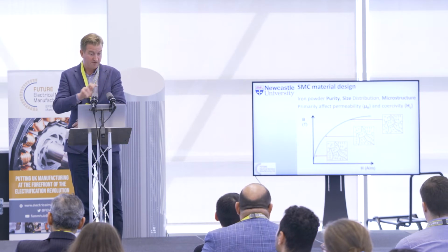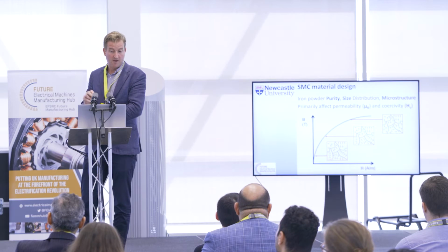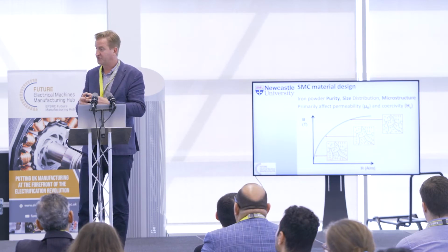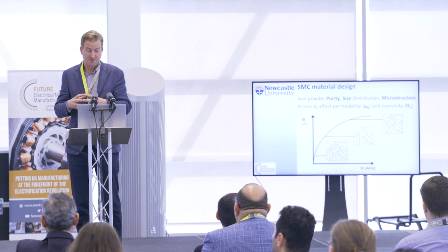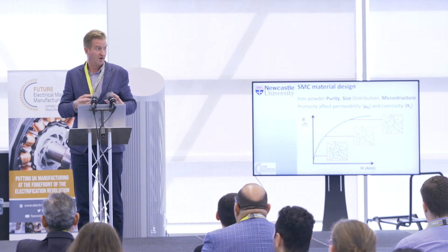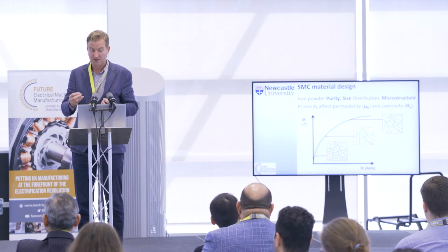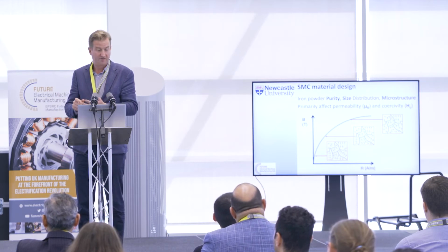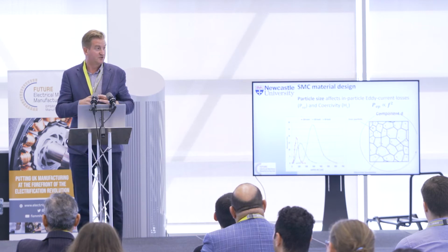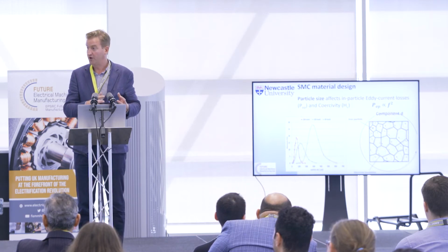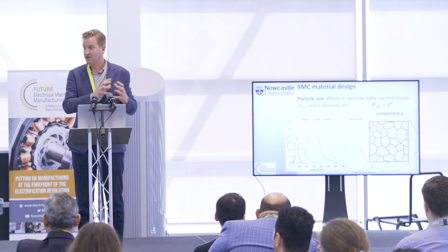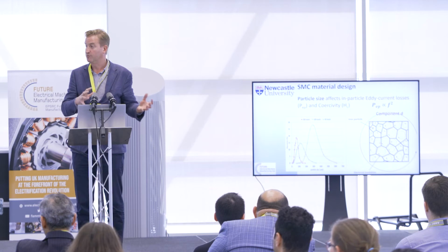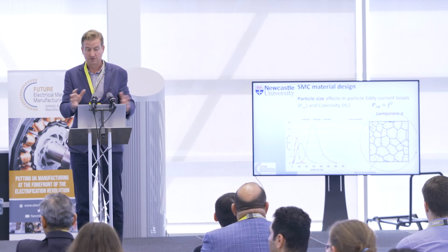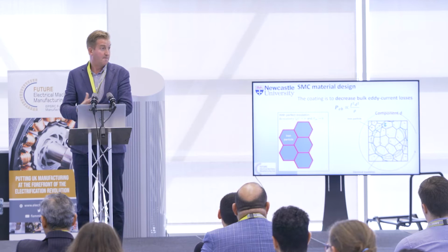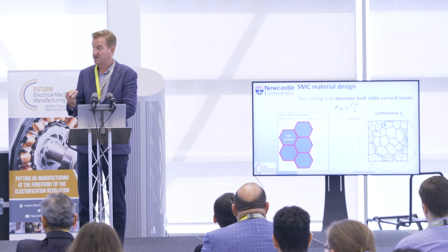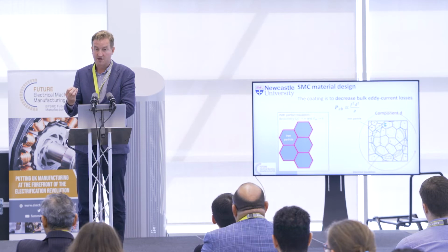Making the soft magnetic composite powder and pressing it is a bit of an art form. There's a balance between getting the purity of the iron right and the distribution of the powder particles. All of that affects permeability, it affects coercivity, and the particle size affects eddy current losses. So when we look at different grades of soft magnetic composite with different loss or different mechanical properties, it's quite often the particle size that is the differentiator there. The coating on the powder also has an effect on the eddy current losses.